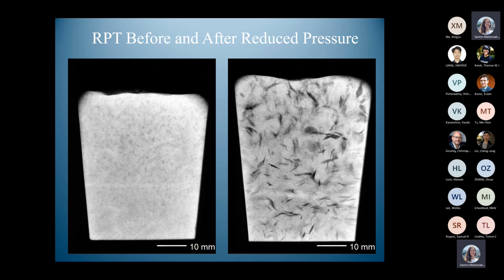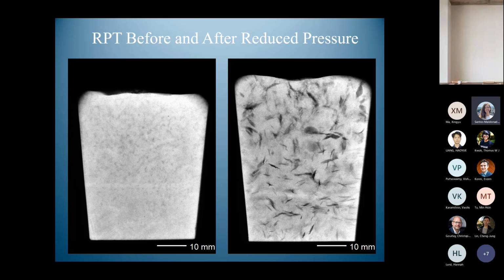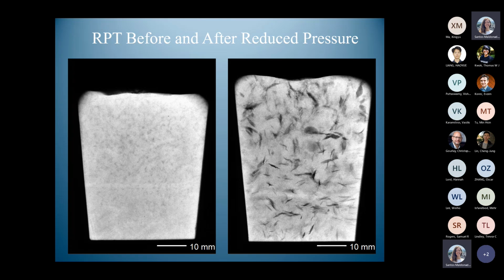And this was a little experiment which was extremely valuable and helpful to us in the early days. It was done many years ago. We took 2 small molds about the size of egg cups. And we took some liquid aluminium and we poured the 2 molds more or less at the same time, same temperature. So the 2 are identical with liquid metal. And over the one on the right, we put a bell jar and we pumped down the pressure to about 1/10 of an atmosphere. Actually, I forget, maybe it was 100th of an atmosphere. But anyway, it was a lower pressure because what we wanted to do was to expand the 2 films apart by lowering the pressure so the air trapped between them would expand, and so we could see them by X-ray, which is what these are.